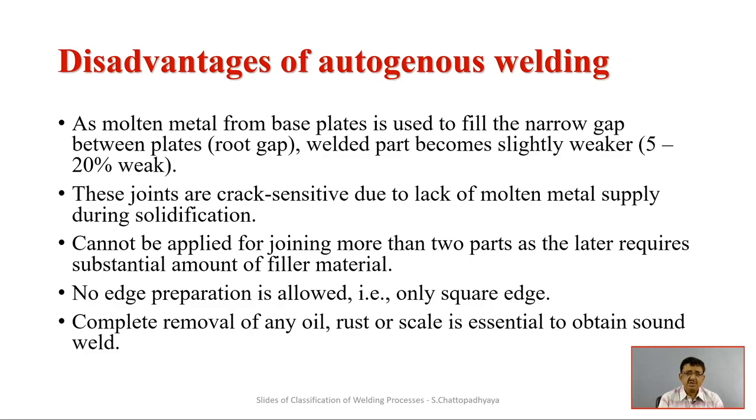So, only square edges will be preferred, and complete removal of any oil and rust is required, because less material will be added, so surface cleaning has to be done. No rust or scale, as it will have a detrimental effect on the sound weld.